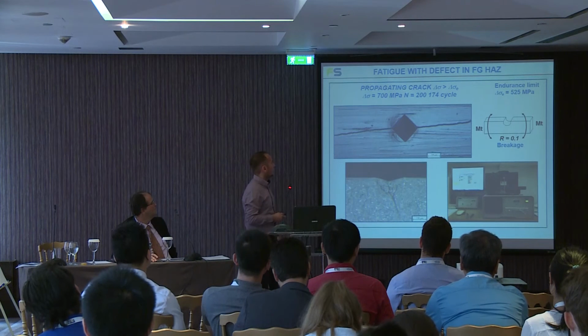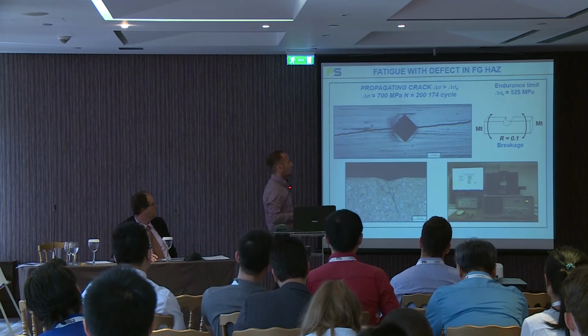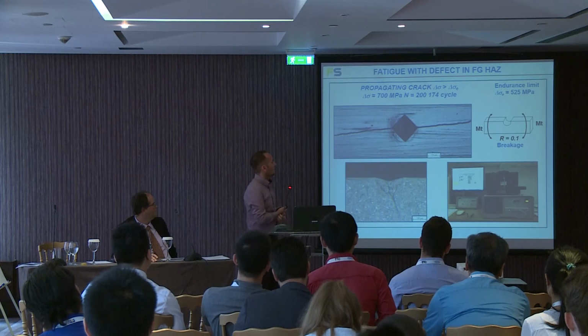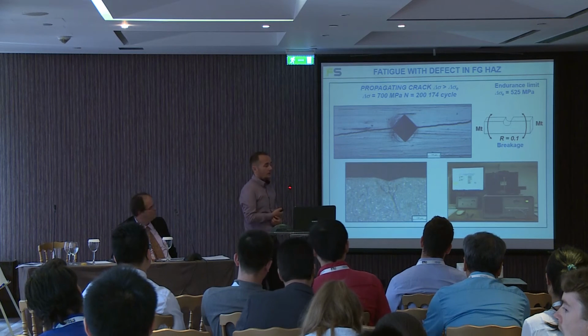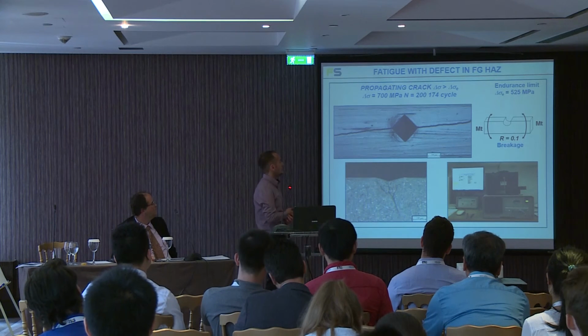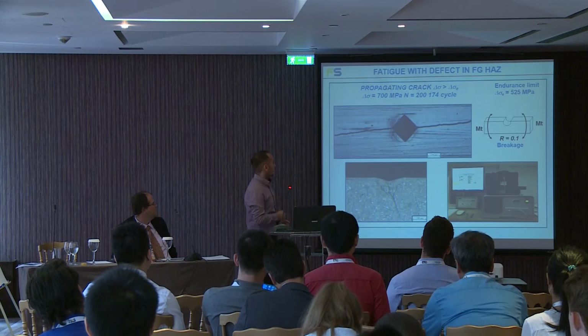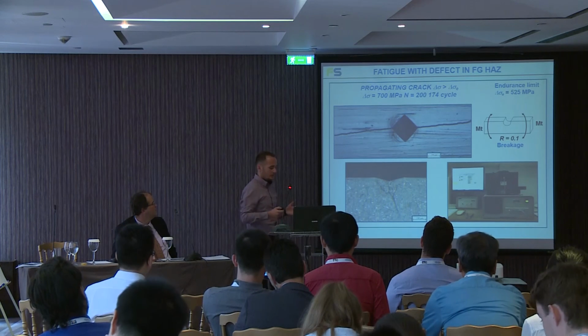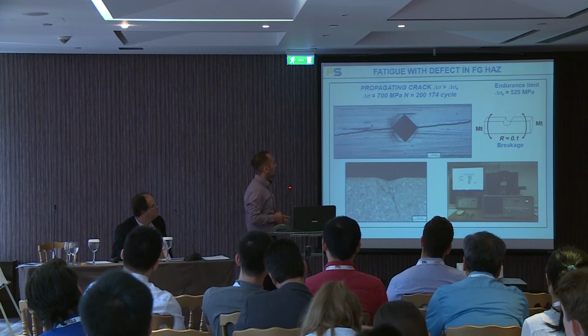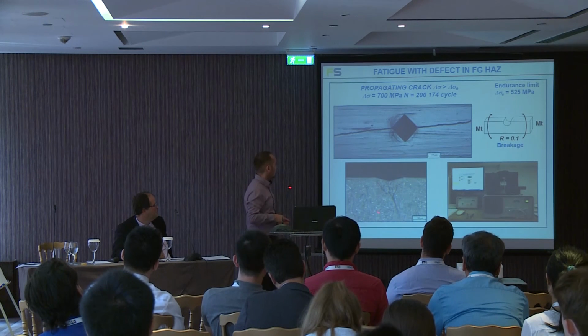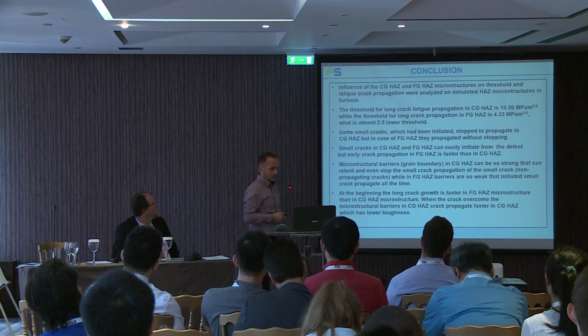This is about the fine grain heat affected zone. We have evaluated the endurance limit, and the endurance limit of the fine grain heat affected zone was 525 megapascal. The crack has propagated along the diagonals of the indentation, and this is about the microstructure of the broken specimens.